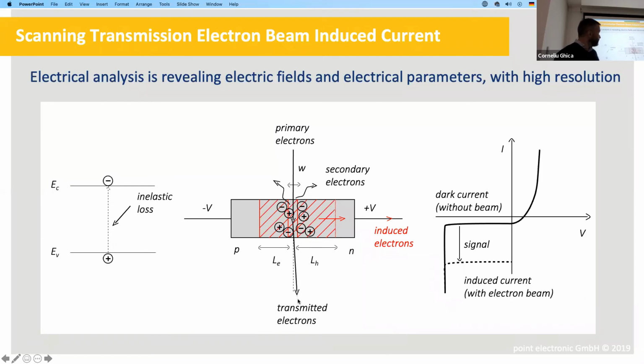Another interesting effect is that transmitted electrons are slightly deviated, or the angle is changed, because of the field they're going through. And that can also be picked up with scanning differential phase contrast. But I'm not going to go into that technique today. All we're going to do today is collect the current that goes through it. In terms of an EBIC curve, and it's the same whether it's SEM or TEM, the signal that we're collecting is this one on the EBIC curve. So we're in the reverse direction, it could be a zero bias, or it could be some bias, and that's the signal we pick up as we scan the beam.